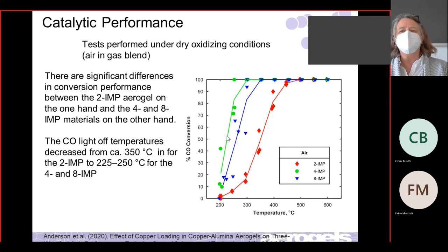So basically what we saw was a pretty big difference between the conversion of the 2 and the 4 and the 8. Given the scatter in the data, the 4 and the 8 are pretty much the same. Maybe the 8 is a little bit different, and might be a little better, but not a lot better, not in the way that 4 is so much better than 2.